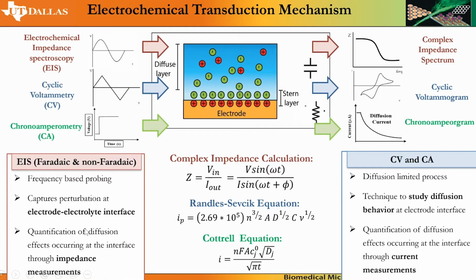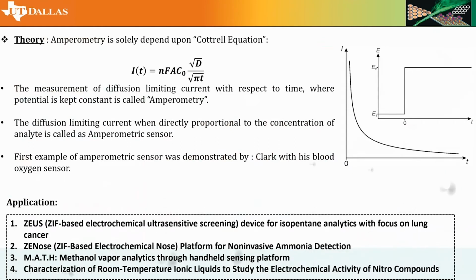It captures the electrode-electrolyte interface perturbation, and quantification of diffusion effects can be done based upon the impedance measurements. On the other hand, cyclic voltammetry and chronoamperometry are based upon a diffusion-limited process, and you can study the diffusion behavior of the target VOCs, how they diffuse inside the modified electrode surface area, and they cause a change in the current measurements on the surface that is quantified as a signal response. So chronoamperometry is the primary electrochemical transduction mechanism that we'll be targeting, and the other techniques we'll use as cross-validation methods to show that our results actually support our hypothesis.